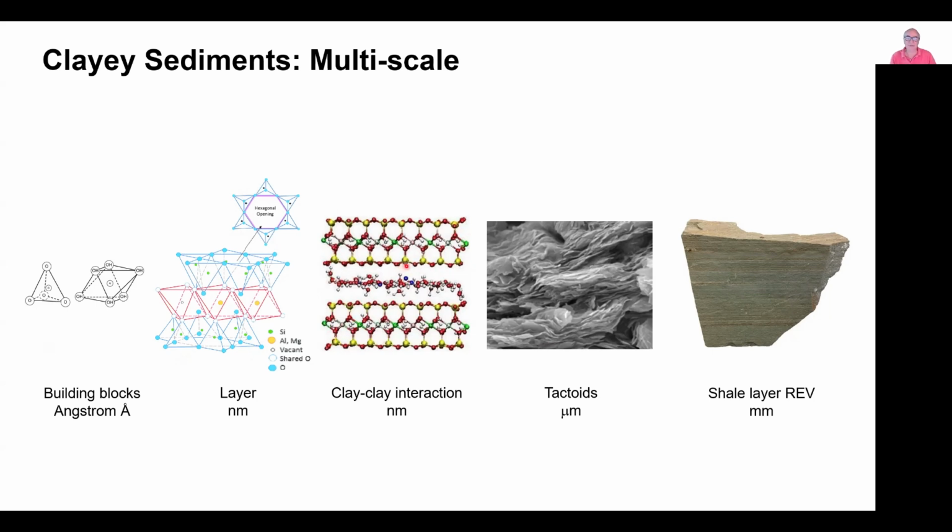By the time we have these layers interacting with water, they become separated, forming the counter-ion cloud. And in this case, you have a 2-to-1 layer separated by water with respect to another 2-to-1 layer. And this is the result of molecular dynamic simulations. And now we are at the nanometer scale. Probably across here, we will have 15, 20 angstroms. So we have 2-3 nanometers across.